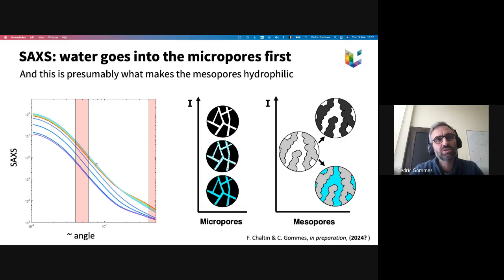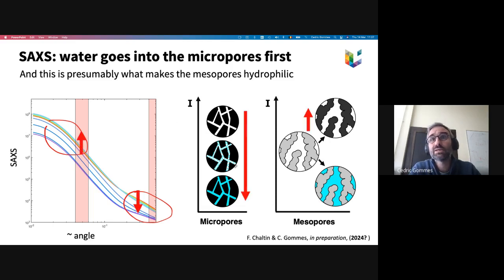consider that the small angle scattering signal depends on the contrast between the phases. Yeah? So here, what I've sketched is the micropore structure and the mesopore structure. At the micropore scale, the relevant contrast is between the carbon and whatever is in the micropores. Yeah? And at mesopore scale, the contrast is between the micropore skeleton and whatever is in the mesopore. Yeah? So when water gets in the micropores, this, of course, decreases the contrast between the carbon and the micropores, and accordingly, this should decrease the scattering intensity in the microporous region, and this is indeed what we see. And simultaneously, when water gets in the microporous skeleton, this should increase the contrast between the empty mesopores and the microporous skeleton, and this is also what we see.